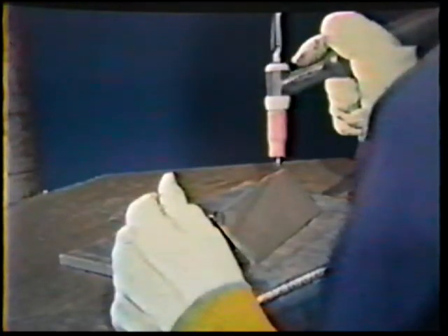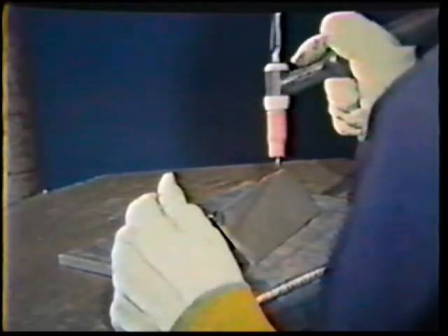Increase the amperage to 75 to 85 amps and weld the joint with filler metal using the same technique as for the 16-gauge material. The filler rod should be 3/32 inch in diameter. Use the same dipping technique as for the 16-gauge. You will probably find that the 11-gauge material is easier to weld due to the larger puddle and slightly slower travel speed.